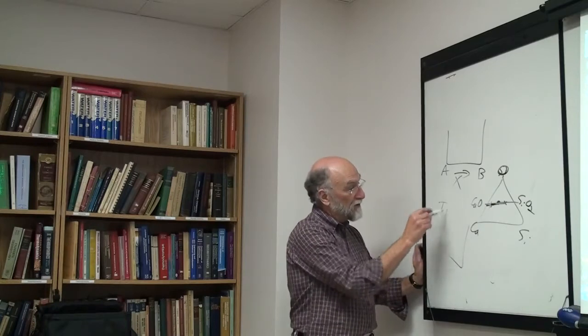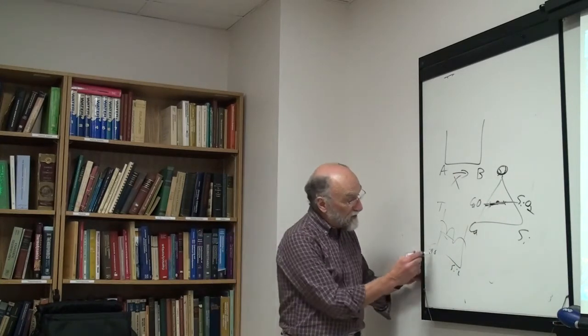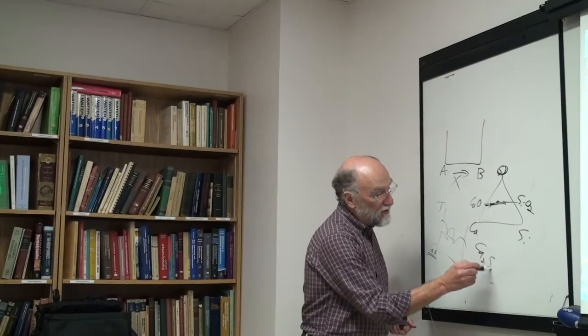In that case, if you draw temperature versus CaO, SiO2 along this line, you do get a diagram that obeys the phase rule for two components. That's a quasi-binary system because every phase is given by that one composition variable. Or you can define your components as CaO and SiO2, and every phase can be defined in those terms. So you have phases like Ca2SiO4, which can be defined in terms of 2 moles of this and 1 mole of this.